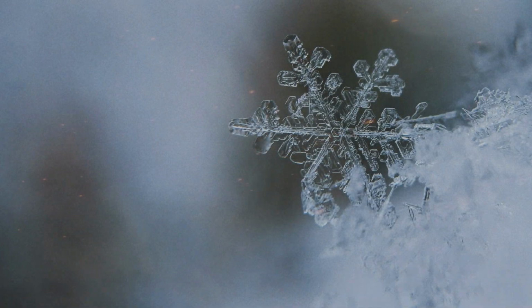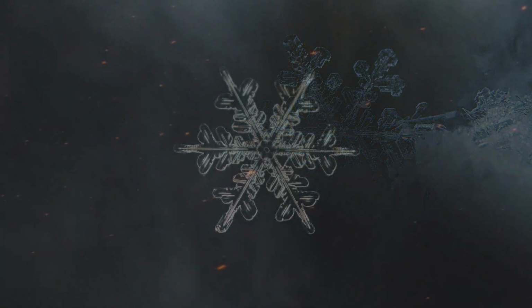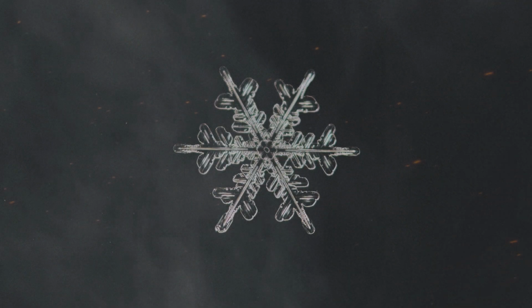But when there is a strong temperature difference between the ground and the surface, a different process begins. Temperature gradient metamorphism occurs when warmer air near the ground and colder air above create a gradient through the snowpack. This gradient drives vapor movement upward. Water molecules sublimate from warmer grains and deposit onto colder ones higher in the layer. Over time, this creates angular, faceted crystals within the snowpack.